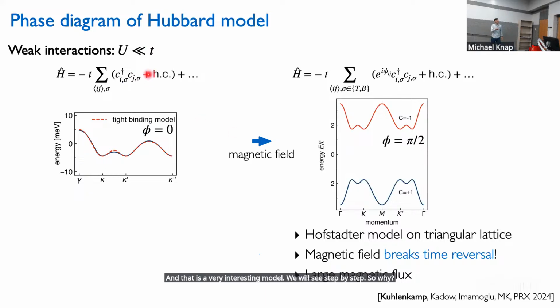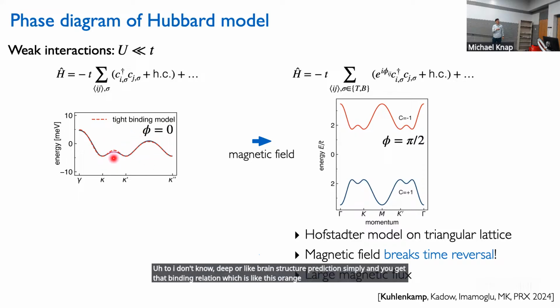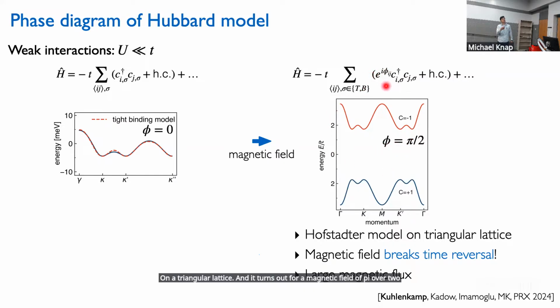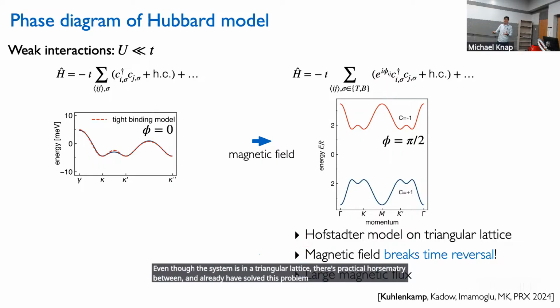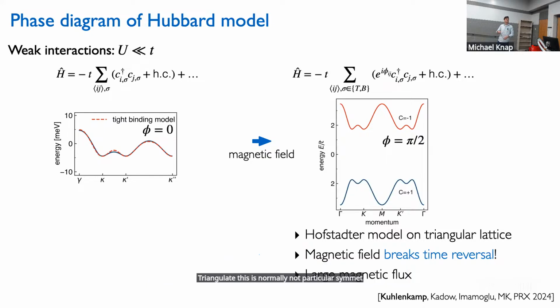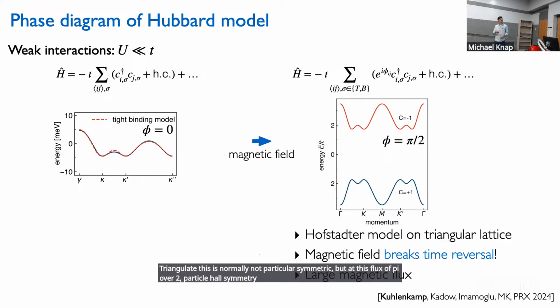So why? First, let's take the limit of weak interactions. Then when we have no magnetic field, we would have some band structure which we can fit to, I don't know, a band structure prediction simply. And we get a tight binding relation, which is this orange dashed line, which agrees well with the full band structure calculation, which is the blue line. We can now switch on a magnetic field, and then what we get is just a Hofstadter model on a triangular lattice. And it turns out for a magnetic flux of pi/2, even though the system is a triangular lattice, there's particle-hole symmetry. It's kind of nice. Triangular lattice is normally not particle-hole symmetric, but at this flux of pi/2, particle-hole symmetry is restored in this system.